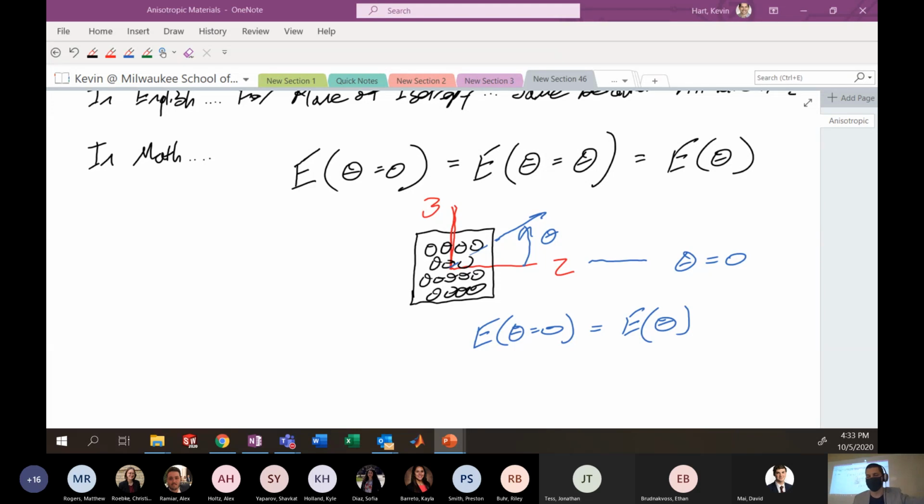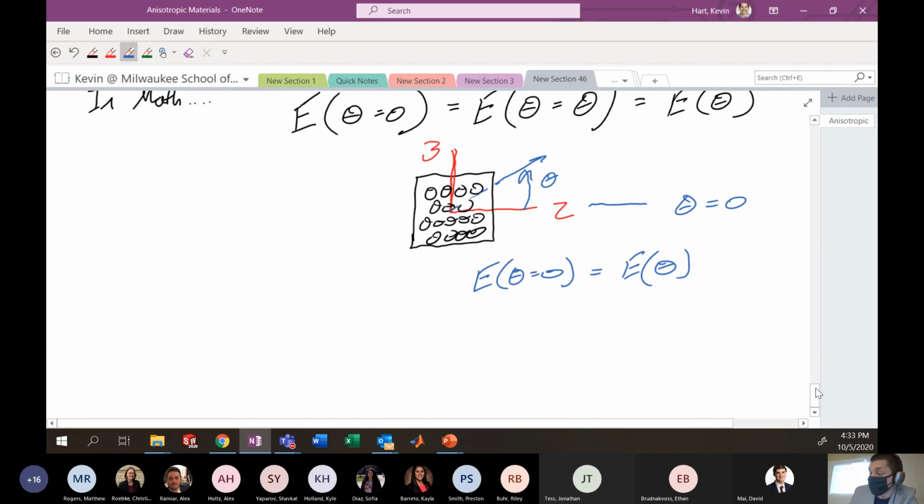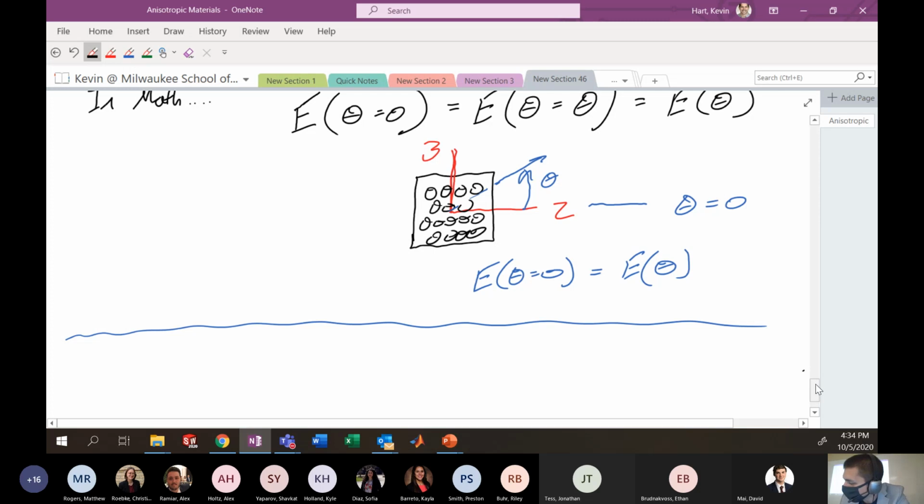If I'm on a plane of symmetry, then the stiffness matrix for my original condition should equal the stiffness matrix of my new 180-degree rotated condition. You equate those together, see what matches and what doesn't, and you can simplify things out. So we're going to do transformations or rotations of our stiffnesses with arbitrary angles and see how these stiffness matrices shake up.